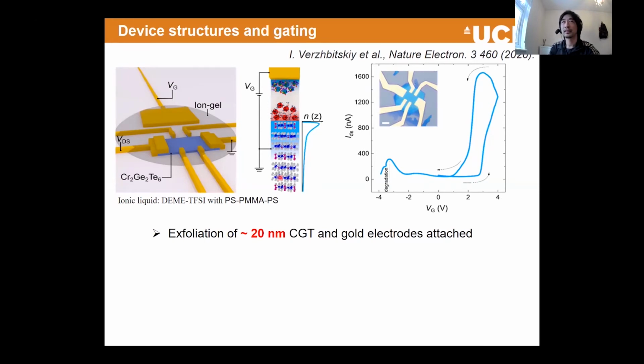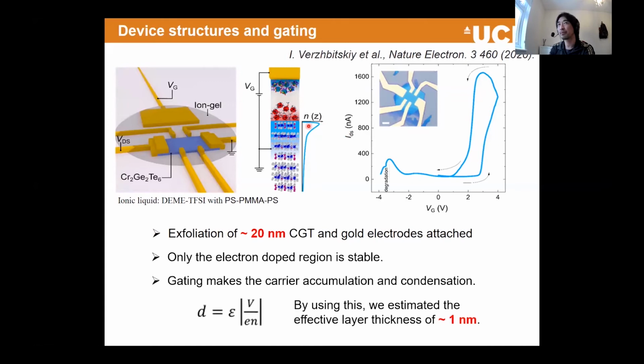And we start with 20 nanometers of CGT. So this is reasonably thick. It's not a few monolayer regime. But what we discovered is that at this doping regime, we accumulate so much charge carrier at the surface, and when we calculated the depth or width of this accumulation, we discovered that it is almost 1 nanometer. So the conduction is happening in just the top 1 nanometer of the CGT material.